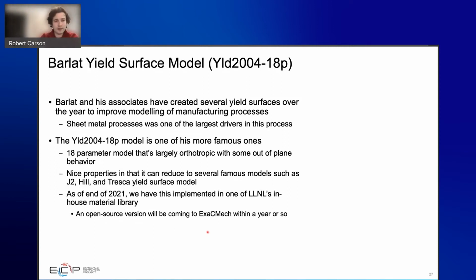As I mentioned, there's been a lot of research in these anisotropic yield surface type models. One of the people who did a lot of work on this was Barlat and several of his associates. Over the years, they've done a lot of work to better model sheet metal forming processes, just because people really don't like wasting material. So having a better model for how sheet metal forming goes really helps. He created a model called the Yld2004-18p model, which is a really clever name, I know, but it's because it came out in 2004 and it has 18 parameters. This model is largely orthotropic, with some out-of-plane behaviors that it's able to capture. One nice property of it is that it can reduce down to several famous models, such as J2, your Hill yield surface, and your Tresca yield surface models.